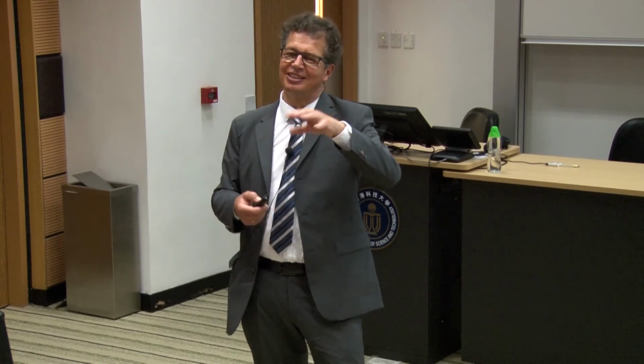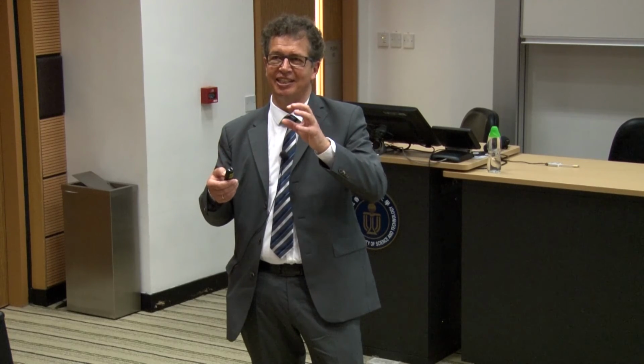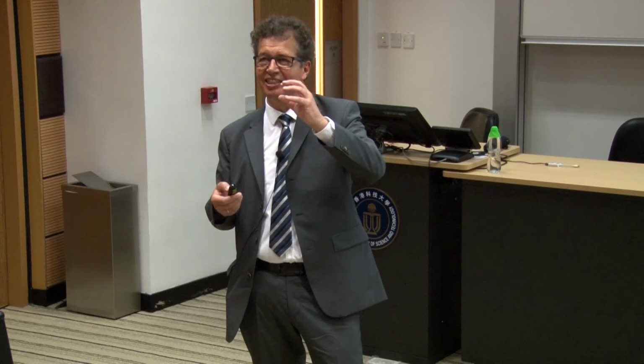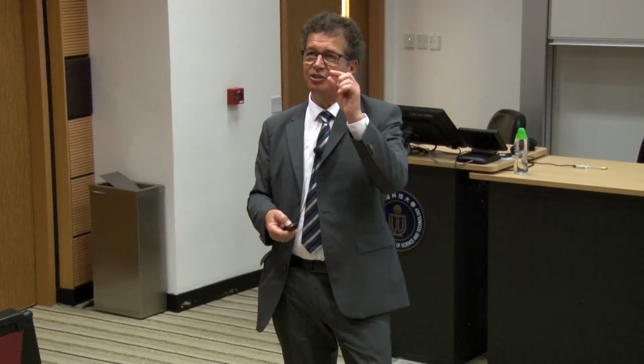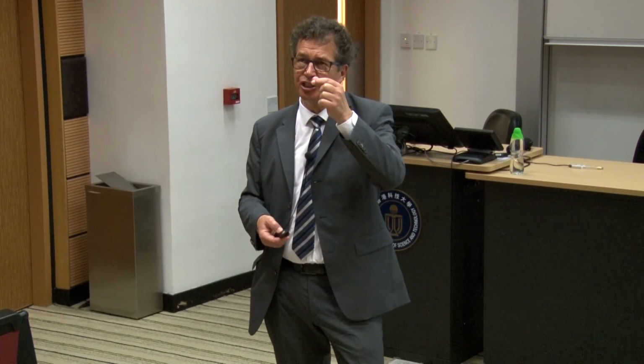We should not neglect the Auger process, but even more, I've shown you that thermal processes should not be neglected, and we are pretty sure that also in these systems, these high laser intensities can induce thermal processes, and we have some indication, I didn't have enough time to go deeply into this, that you can even get a transformation due to this energy from anatase to rutile in this system. So we find, after just one or two laser pulses, some rutilized crystals. So this thermal energy is sufficient not only to bring about the Auger process, I totally agree with what you cited from the literature, but also bring about the transformation to the thermodynamically more stable form, which is the rutile form.